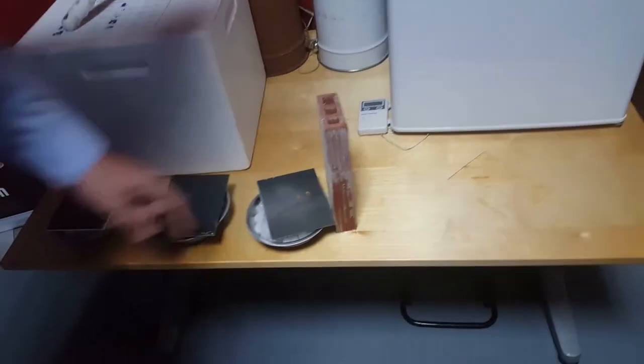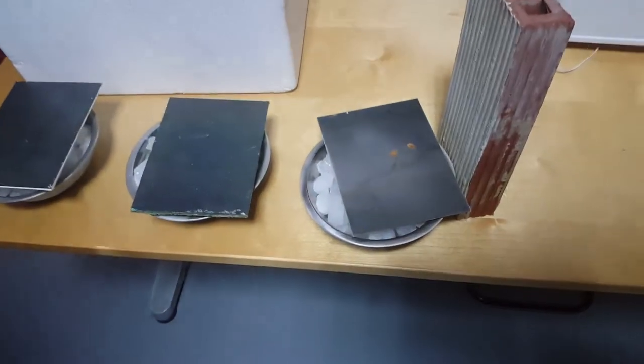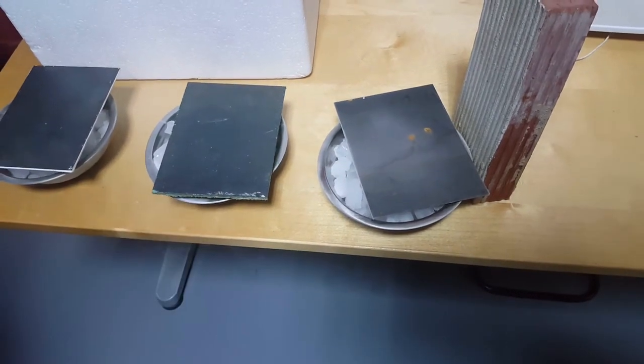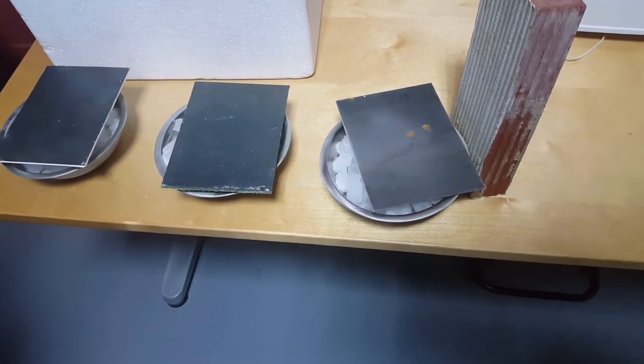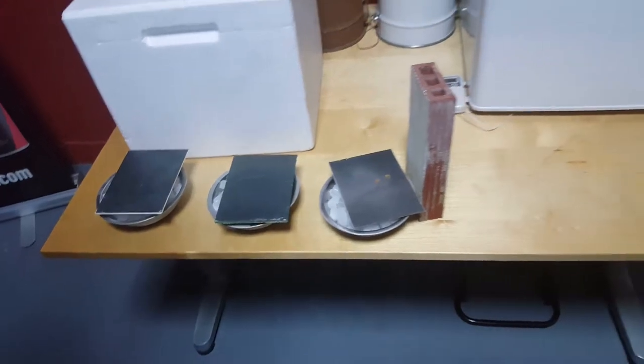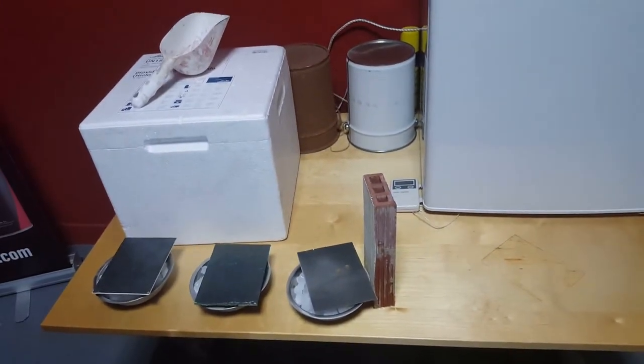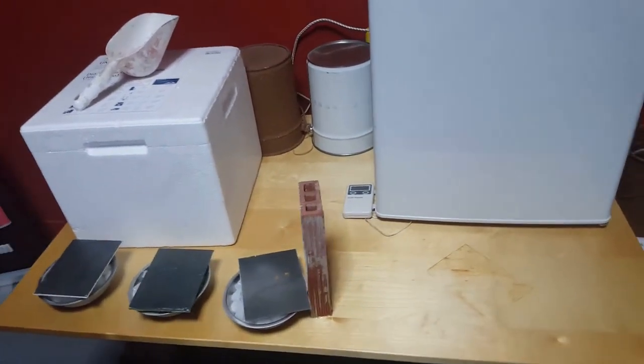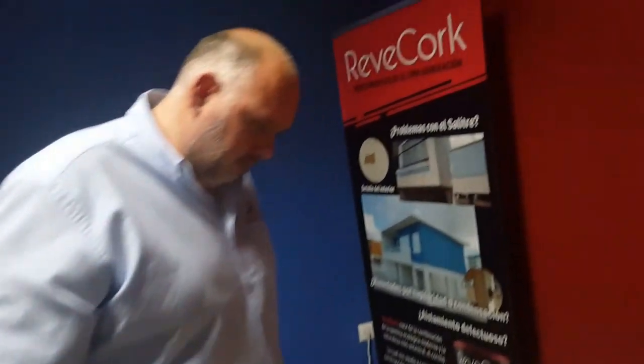We can see here that the side of the uncoated sample facing the room has started to have some condensation form on the top, and the condensation is refreezing because that dry ice is so cold. The other two samples, both the cork and the ceramic, do not show any signs of condensation because they are slowing the transfer of that cold into the metal plate.